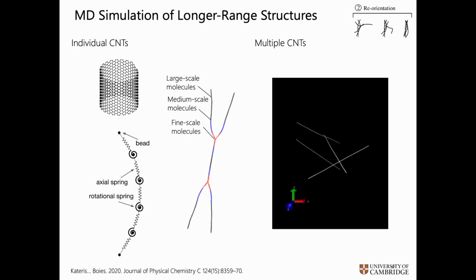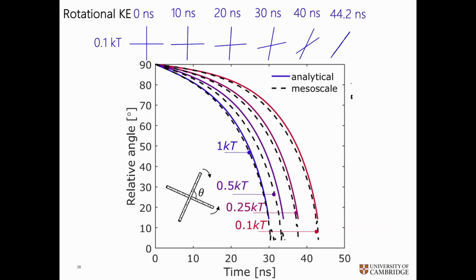And so we can simulate this. We've been working on this a while, of taking nanotubes into a simulation domain. We can simulate kind of every atom, but frankly, we run out of computational power very quickly when one goes to hundreds of microns or millimeters long. So we have to be a bit smarter in the algorithms we're putting in. So we parameterize bead spring models with atomistic models, and you're able to describe this. And what's interesting is that we get a process where we think of it as kind of the reorientation or the coalescence. If it was two water droplets coming together, you would think of those water droplets coalescing into a sphere. This is kind of the analogous process of two rods coalescing into a single rod.